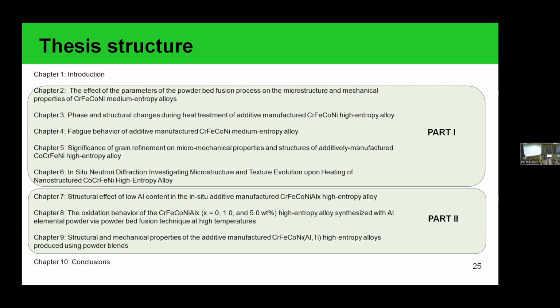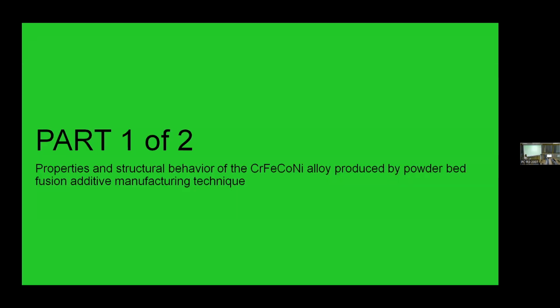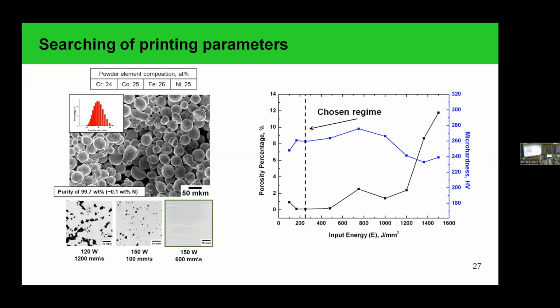And the data can be divided into 2 parts. The first part focuses on the properties of this 4-component system, and the second part demonstrates the properties of the in situ alloyed materials. So coming to part 1. In the first stage, we observed the morphology and the quality of the powder, and we see that the particle distribution is quite good for the PBF process. The element composition, according to EDX analysis, demonstrates an approximately equiatomic portion of each element, but the purity is about 99.7% with 0.1% of nitrogen.